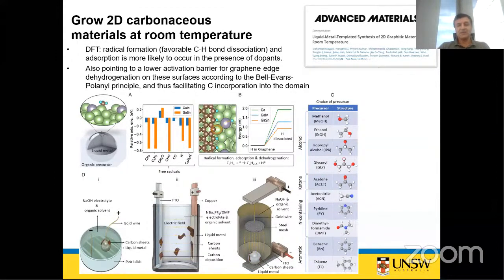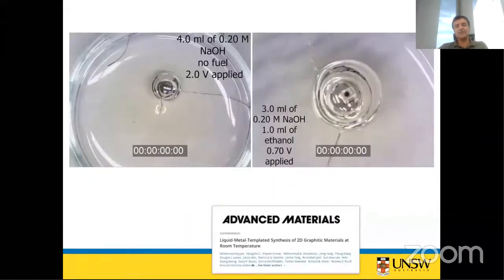And if you have tin and indium together with gallium, this happens more efficiently. And on the other side, we also have radicals after dehydrogenation. Radicals which are produced can penetrate and then form CC bonds in the liquid metal. The bonds make the entity bigger and bigger, and this entity cannot remain dissolved and comes to the surface. So, very interesting reaction media.